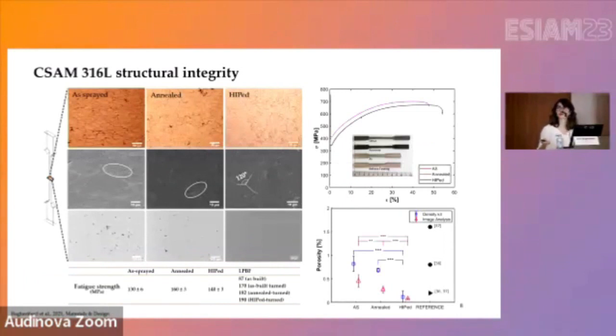Again, the microstructure of the cold spray sample, where you can see the classic, let's say, packing of the pancakes, the powders that are flattened on top of each other. After annealing, the boundaries are a little bit more faded, and we are promoting the metallurgical bonding. And then after HIPing, we are almost recrystallizing the structure. Here is the static tensile response of the samples. In as-built condition, we have very low ductility, very brittle behavior, but after annealing and HIPing, we are recovering a notable ductility. In terms of porosity, with different methods and different configurations, we are always at about 1% porosity.